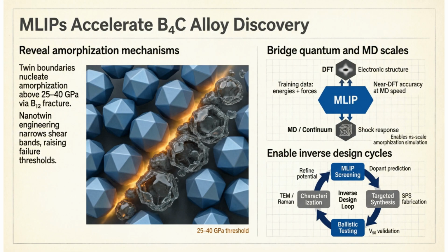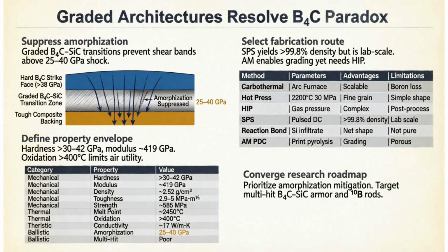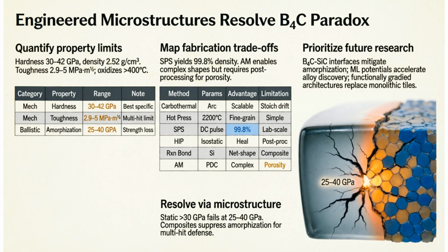Machine learning interatomic potentials, or MLIPs, are accelerating alloy discovery by bridging the gap between quantum electronic structures and MD-scale shock response, enabling new inverse design cycles. Graded architectures are a key breakthrough for resolving the paradox. By transitioning from a hard boron carbide strike face to a tough composite backing, we can effectively suppress harmful shear band propagation. The future research roadmap prioritizes amorphization mitigation.